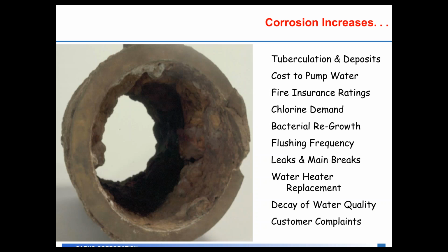So if you have corrosion issues out in your distribution system, there are many issues and hallmarks you could see out there that let you know these problems are going on. The first one is, it's not very often that you get to go out to the distribution system and cut sections of the pipe like you see in the picture, but obviously you could have tuberculation and deposits on the inside of the pipe. In this case, in the cast iron pipe, that's calcium carbonate scale mixed in with iron to cause the rusty red tuberculation you see on the inside of the pipe.